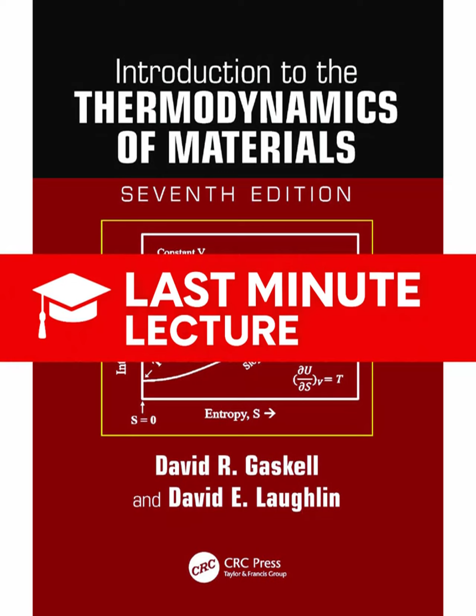Okay, so as Cp and ΔH are established, we have to tackle the final piece of this puzzle, entropy, and specifically the third law of thermodynamics. Why was this so important to figure out? Well, this was the holy grail for physical chemists in the early 20th century. They had the Gibbs-Helmholtz equation, the master equation. They knew ΔH and ΔS changed with temperature, but to integrate them and get the full picture of ΔG versus T, they needed the integration constant. They needed to know the entropy change at absolute zero. Without that constant, they were stuck. They couldn't calculate equilibrium constants from first principles?